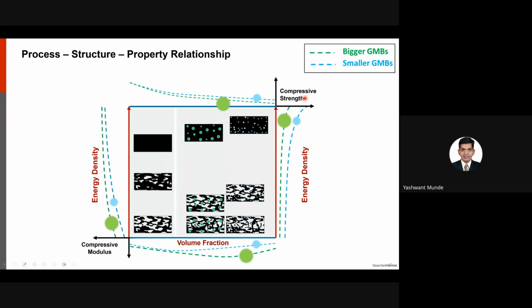In terms of compressive strength, we see that as the energy density increases, the compressive strength increases because of better contact and confinement of the particles, and the smaller particles show a higher improvement in the compressive strength. In both cases the strength decreases with increase in volume fraction, so we want to limit that to a smaller volume fraction.